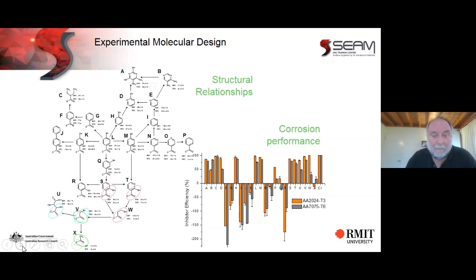So this was work done by Tim Harvey at CSIRO, looking at a family of inhibitors called the capto compounds. It's quite complicated, but all that I want you to really see is that if we change the inhibitor chemistry in small ways, we can dramatically change whether it is a corrosion inhibitor or in fact whether it promotes corrosion. On the left-hand side are the different molecular structures, and down the right-hand bottom is the inhibition efficiency, where something on the top is between 90 and 100% efficient. That's a very good corrosion inhibitor, which will cut corrosion down to anywhere from 1 to 10%. If we're on the bottom of that graph, though, we're actually promoting corrosion.